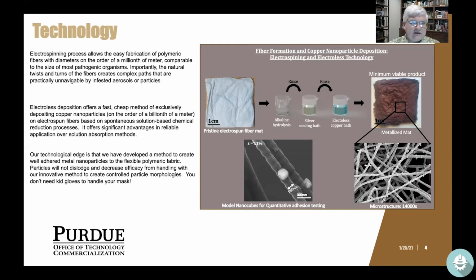And our particular technology is we've looked at a way to get a specific geometry where the nanocubes are well-adhered and conform to the shape of that polymer fiber. And it's that conformal condition that leads to an extremely high adhesion of the particle to the underlying fiber. And you can see there in the picture, we stretched individual nanofibers to strains of 10, 11, up to 17%. And we see the particles remain on, even when the polymer starts to fail, the particle stays adhered.